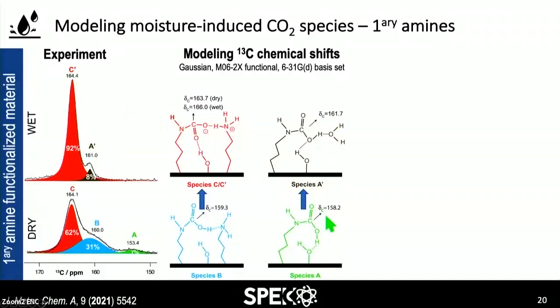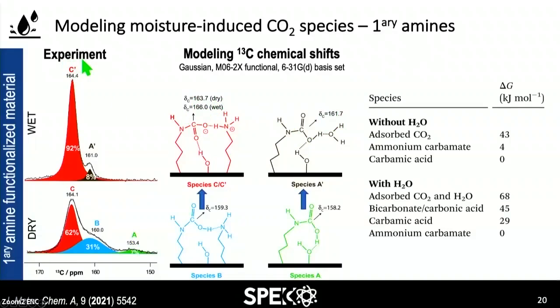And as you can see here, this chemical shift, this one here, when it's hydrogen bonded, it goes to 161. And here as well, you can see that depending on if this carbon is under dry or wet environment, you can see that they fall into more or less the red part here. And if you compare the Gibbs energy difference, you can also see that under wet conditions, the most stable species is ammonium carbamate and not bicarbonate.